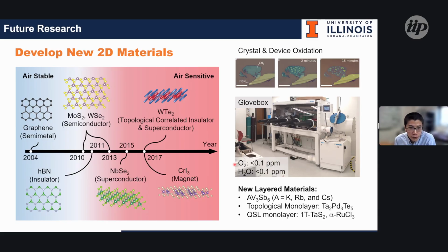Yes, that's a great question. So we had to try to push along this direction, but the spectroscopy measurement so far has been extremely limited, especially in this twisted tungsten ditelluride system. The main reason is because this material is extremely air sensitive. So to fabricate it, you have to encapsulate this material with hexagonal boron nitride, which is extremely limiting for the STM study.